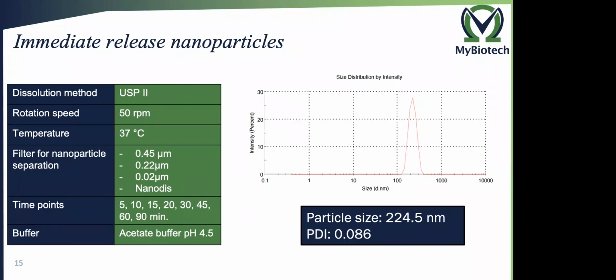Again, our method: USP2, 50 rotations per minute, 37 degrees. We have used four different filters: 0.45 micrometer, 0.22 micrometer, 0.02 micrometer, and the Nanodis, whereas I have to say it was really hard to get the dissolution medium through the 0.02 micrometer filter because we tested the ibuprofen in the real dose, which means 200 milligrams in 900 milliliter dissolution medium. Together with the other excipients that we use for the tablet formulation, it is a high concentration of nanoparticles in the dissolution medium, and it directly blocks the smaller filters.